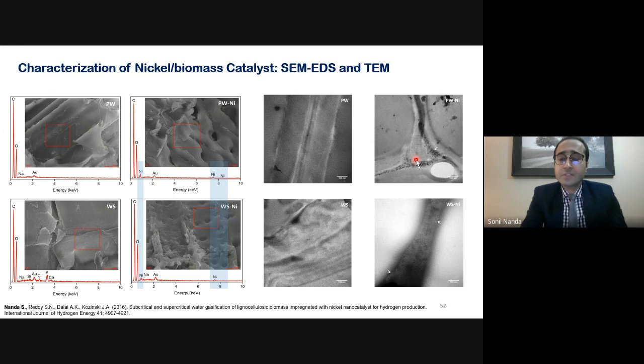Now, these are the transmission electron microscopy images of control pine wood as well as the nickel impregnated pine wood. Once again, you can see this is the cell wall, and these are some of the droplet-like structures, fine dots. These are nothing but the nickel nanoparticles that were generated in the pine wood cell, and these are the wheat straw. Once again, fine dot-like structures. If it is still visible at your resolution, you can see that these fine dot-like structures are nothing but the nickel nanoparticles, which were confirmed in the SEM-EDS studies and also seen in the transmission electron microscopy.